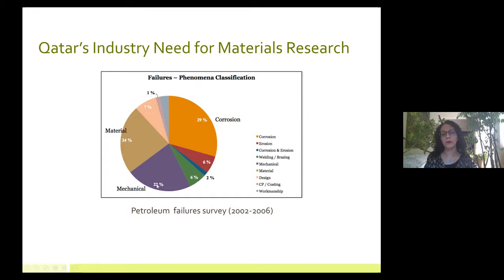We see things that are quite interesting, like welding. 6% of the failures were due to welding, 7% were due to poor design. And we see, for example, erosion. We see a lot of erosion, especially in the external surfaces of pipelines that are above the ground, and that's because of the sandstorms. So we see external erosion, but we also have a lot of internal erosion due to fluid. But all that says that Qatar actually needs a lot of work and a lot of material research because of these issues.